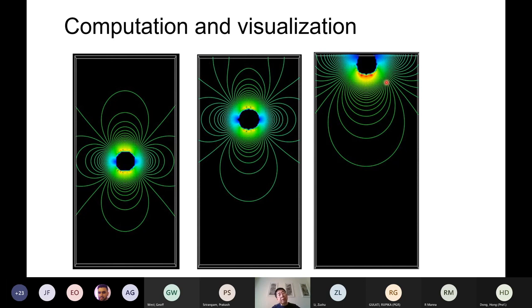So here are three different cases. If we have an inclusion, in the first case located at the center, next time you locate it at another point, moving toward the boundary, and then next time you actually put it close to the surface. So in three different cases, we can get a current distribution. This is a contour of the electric current, okay? And you see that the electric current distribution is completely different. If we substitute this current distribution into our equation, which we just derived, we will be able to know that in different cases, the electric current free energy will be different, okay?